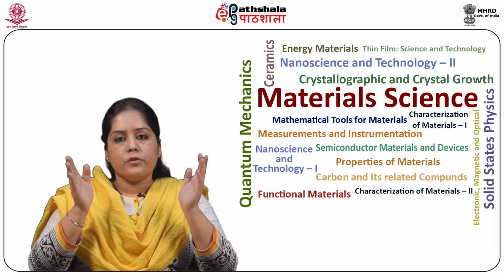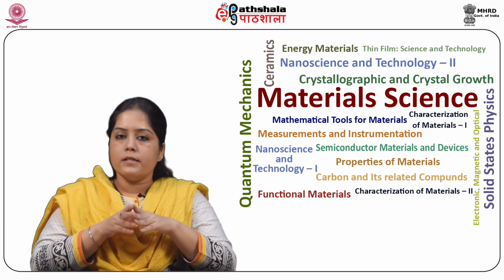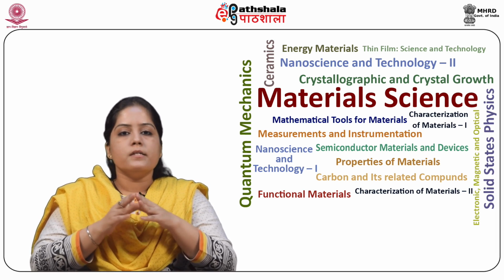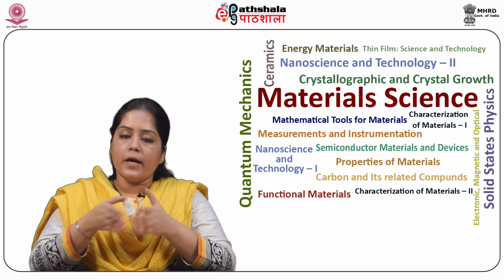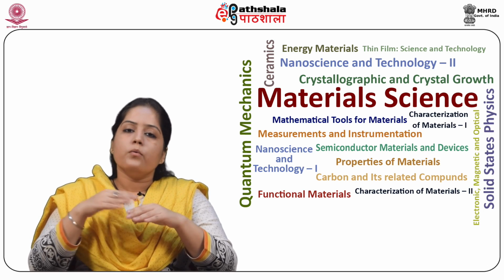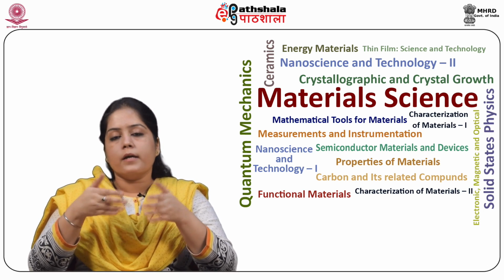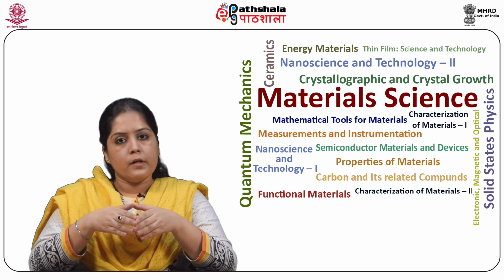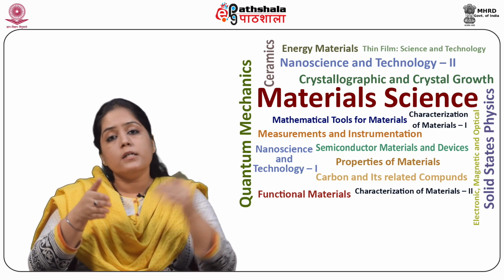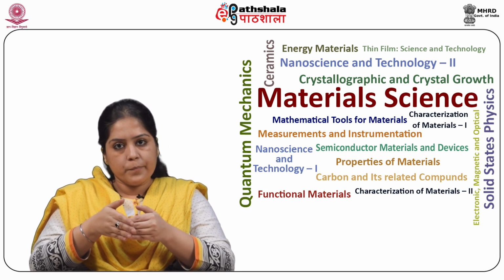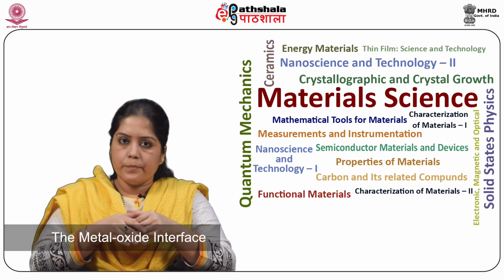Several kinds of defects can develop in the growing oxide scale. These include porosities, cavities, and microcracks. With increasing oxide thickness, macrocracks may appear. Macrocracks allow the environment to directly react with the metal at the metal-oxide interface.